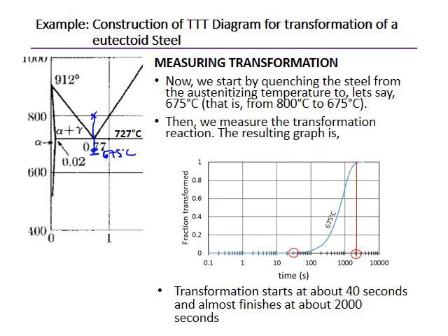Normally we have a liquid media at this temperature. Could be a molten salt, like molten sodium chloride, or it can also be a molten metal, like lead, zinc, or some other metals that are liquid at the temperature of interest. You can also use oil, because oil can be heated to higher temperatures than 100 Celsius. So there are different ways of doing this.